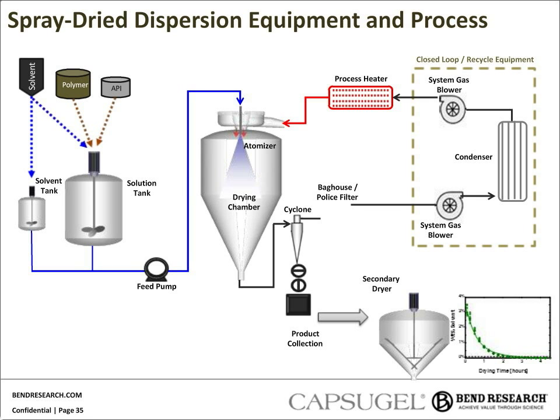On this slide, we have a general layout of a typical spray drying equipment train for SDD manufacture. We begin by dissolving a drug and a polymer in a solvent or a solvent blend to make a spray solution. That feed solution is then pumped to a nozzle where it is atomized into droplets. Those droplets are contacted concurrently with a hot drying gas stream, usually nitrogen due to the flammable nature of the solvents and dust that we work with. That drying gas is also introduced at the top of the spray dryer.